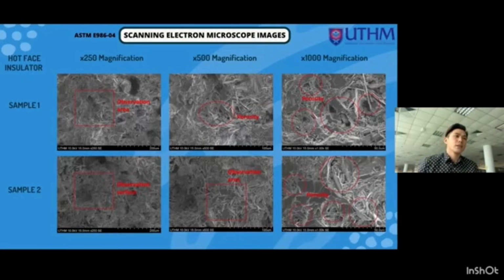So the first part is the hot face insulator, for sample 1 and sample 2. It consists of different magnifications, which are 250, 500, and also 1000 magnification. As we can see, the left part is the observation area and also the surface. Then we zoom into the 500 magnification to observe what is inside the observation area and surface. Then we zoom into the 1000 magnification to observe what is really inside the observation area. So we found the porosity. There are several pores inside the surface.